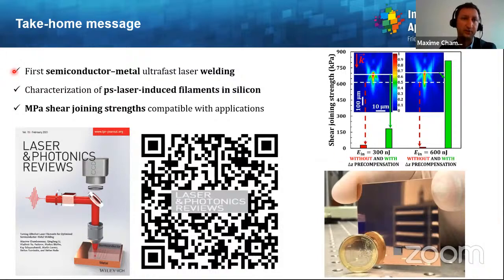We demonstrated the first semiconductor and metal ultrafast laser welding because we characterized the filamentation induced by picosecond laser pulses inside silicon. Besides, we have demonstrated that megapascal shear joining strength were achievable, which are compatible with applications. If you want more details, you can scan this QR code here, which will lead you to our latest publication on the topic, which made the cover of Laser and Photonics Reviews a few weeks ago.